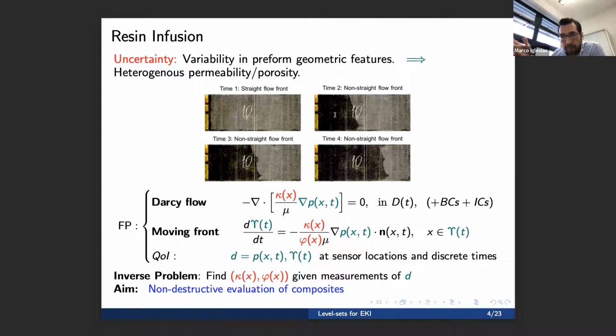So what we have proposed, as a way to have some non-destructive evaluation of these composite parts, which tend to be wasted a lot, is to actually collect data during the resin infusion and then try to infer these properties, and by doing so, flag some potential regions of anomalies. So the infusion of resin is modeled with the equations that you see here.